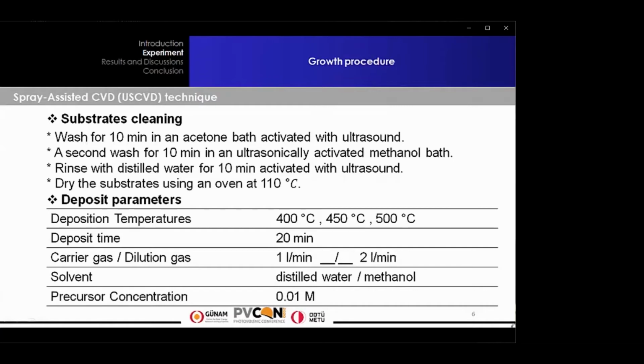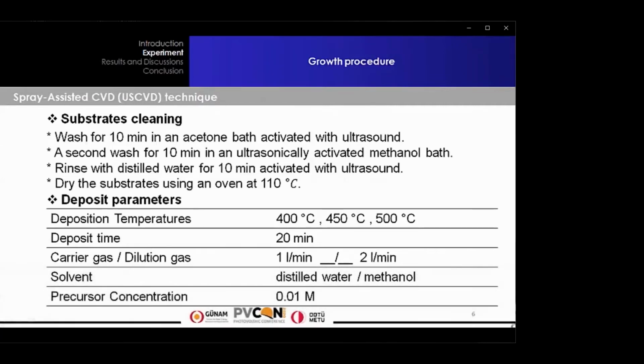Then, ZnS solutions were prepared using zinc chloride as the zinc source and thiourea as the sulfur source. The required quantity of precursor was dissolved using distilled water or methanol or mixed distilled water and methanol in a glass beaker. After, our substrates are placed on the heating plates in the reactor at the desired temperature.